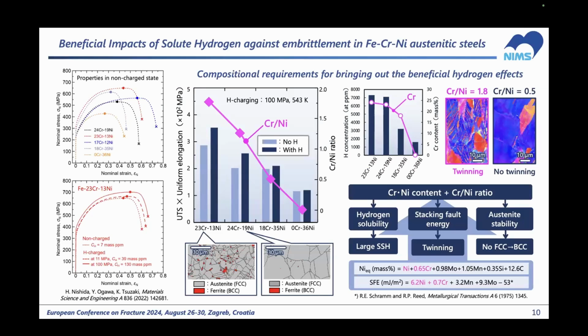So finally, what I talk about is the requirement for the onset of such a positive hydrogen effect in iron-chromium-nickel-based chemical compositions. In conclusion, we found two requirements for the onset of the positive hydrogen effect. The first requirement is the magnitude of chromium content in the alloy, which should be greater than 20 mass% in total. As you can see from this diagram, the bar shows the hydrogen concentration, which was attained by the hydrogen charging under fixed pressure and temperature conditions. With the increase of chromium content, the solubility of hydrogen was also increased, which resulted in an enhanced solid solution hardening effect.